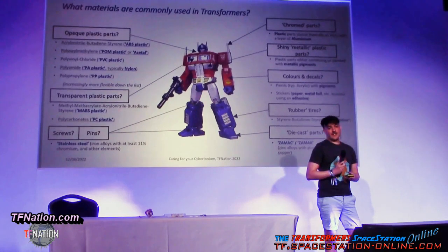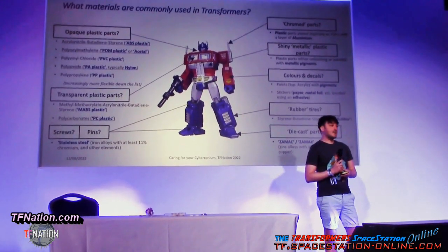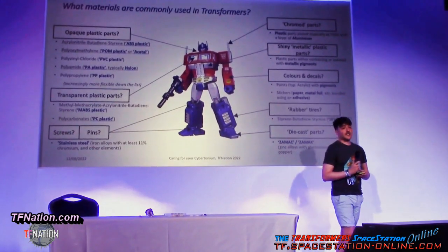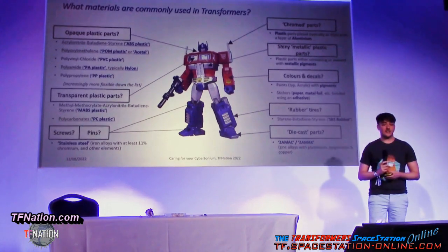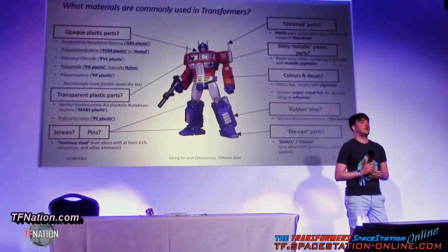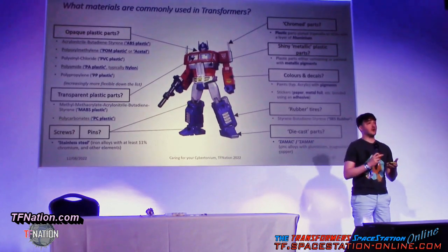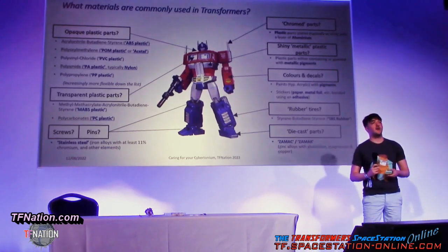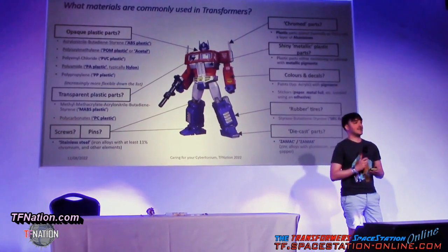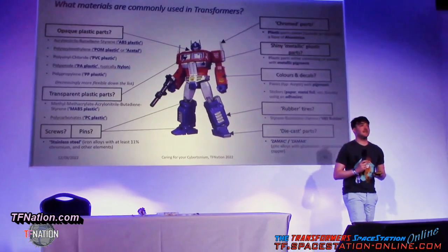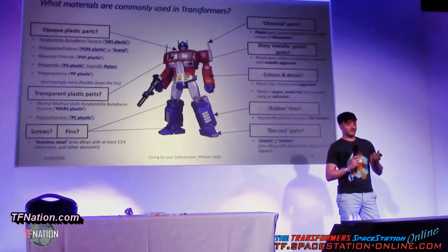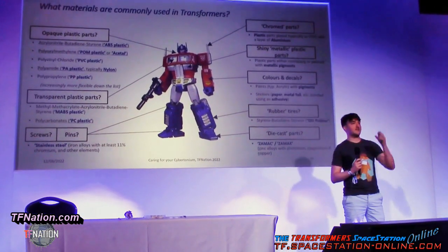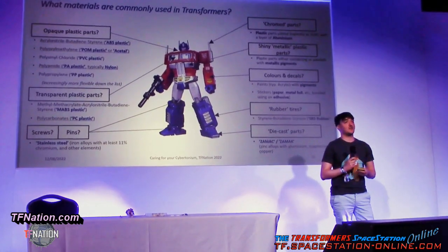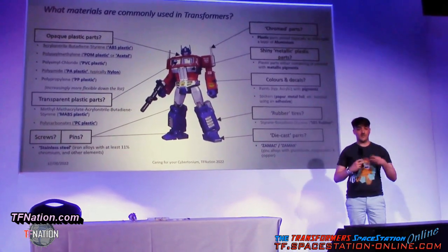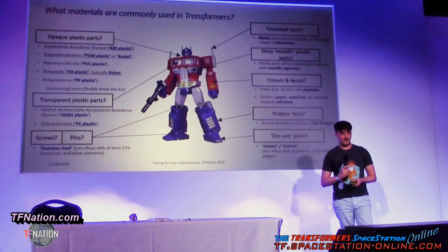For chrome plastic parts, they are just plastic parts and they are coated in aluminium, usually by a process called vapor deposition. You put the entire mold on a sprue inside a vacuum chamber, you fire off a particle against a slab of aluminium, and the aluminium releases a molecule, or an atom, a chunk, and it flies down and impacts onto the plastic and adheres. It forms a layer of aluminium.